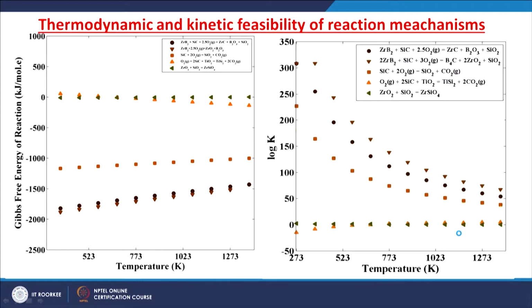Gibbs free energy versus temperature was plotted for these reactions, and we can see the formation of zirconium carbide, boron oxide or silicon oxide. It is feasible within this temperature range of around 500 to 1273 Kelvin. Within this range, these are largely negative, which means it is a highly possible reaction. Similarly, zirconium oxide and zirconium carbide. Silicon oxide is usually formed on the silicon carbide surfaces at high temperature.